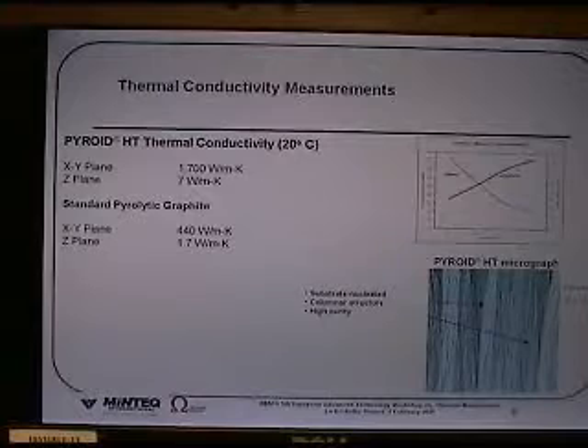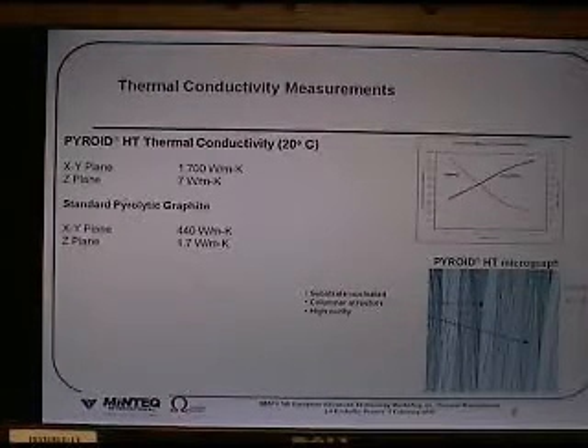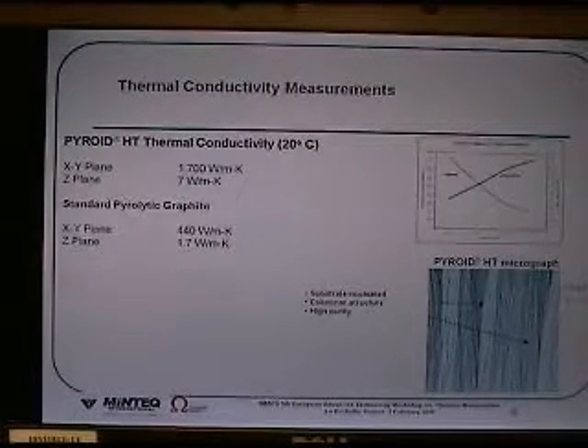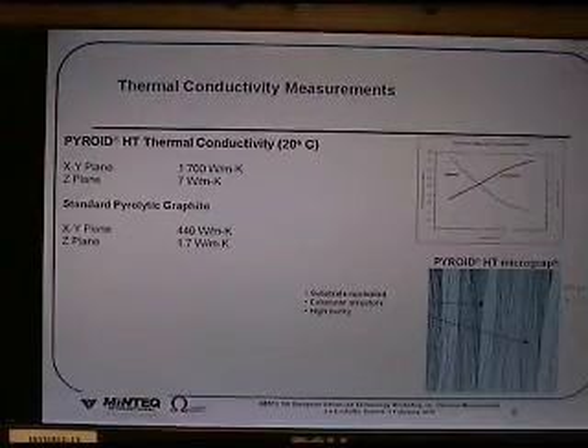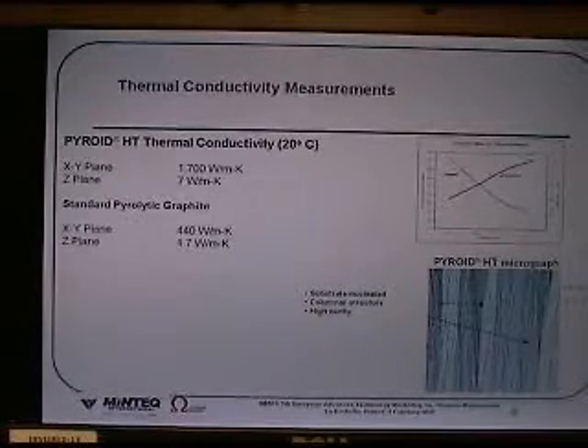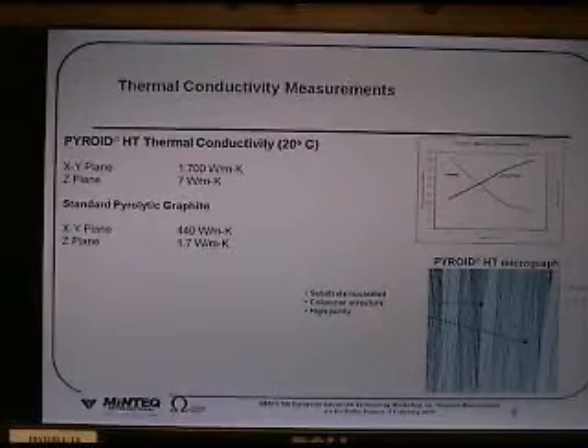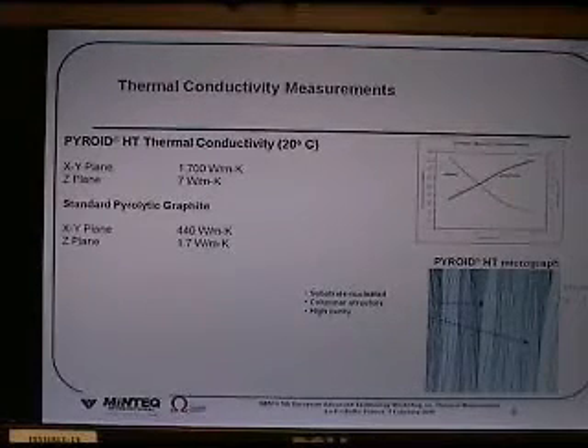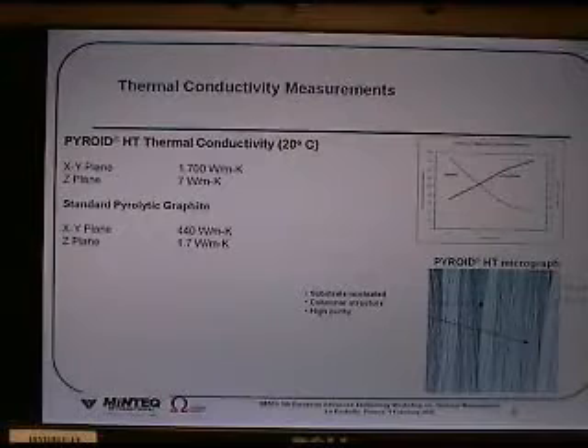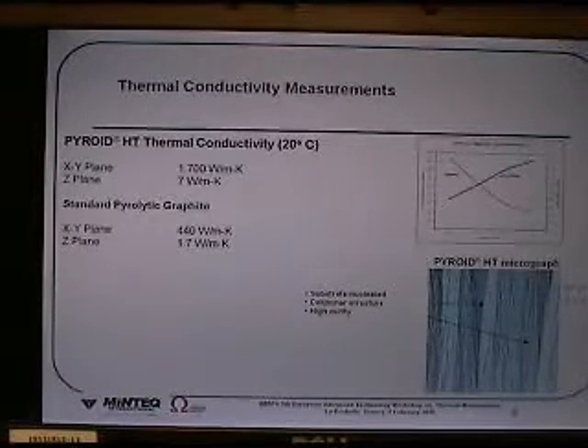The metallization technology that we've developed also allows us to contact our material to a wide variety of devices. This further illustrates the thermal conductivity measurements that we've done with both laser flash diffusivity and ASTM D5470 techniques. In the XY plane, it is 1700 watts per meter K repeatably. In the Z plane, it's a near insulator, having only a thermal conductivity of 7 watts per meter K. Comparison to standard pyrolytic graphite is stunning in that we have over a 4 times increase in our high conductivity plane, and in fact approaching diamond at 2000 watts per meter K.